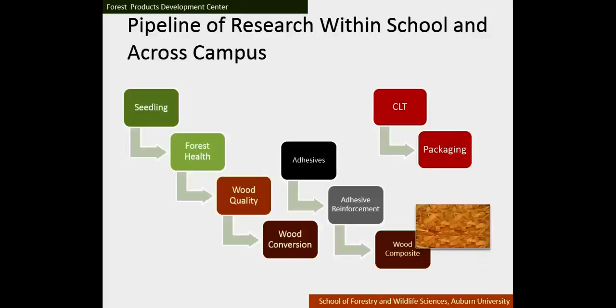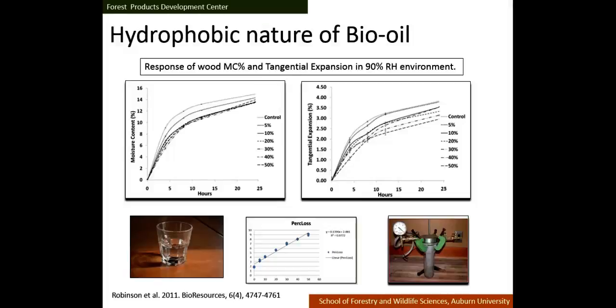So then finally with the wood composite, we've done some work with bio oil, and maybe 4 or 5 years ago we looked at impregnating bio oil in the wood. I'm sure this is no surprise to some folks in the room, it does a good job against high humidities. So if you put bio oil in the wood, it helps the wood retard that higher humidity for a short period of time. But if you dump it in water, the oil will leach out because it hasn't linked to anything. So that's what that bottom graph shows. If we throw the wood in water, it has oil in it, it will leach out into the water.